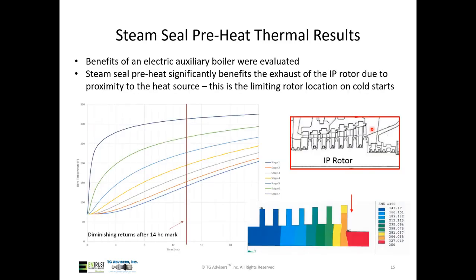So I mentioned the steam seals. Here's an intermediate pressure rotor, and what's interesting is here's the inlet, right? And then here's the exhaust and the gland or the steam seal area. So what's interesting is that the slowest part and the limiting part of the rotor to heat up is going to be this back end typically, because the steam is coming through the inlet and it drops temperature, drops pressure by the time you get back here. This is also the thickest part of the rotor. So it's going to heat the slowest.